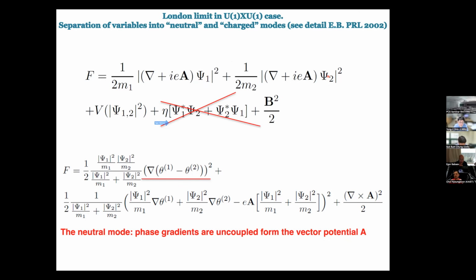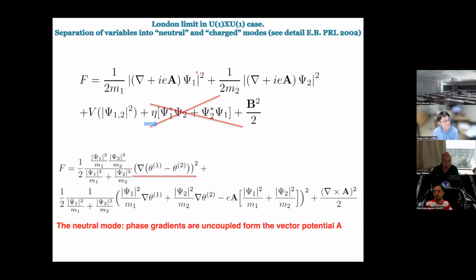Now, there is one important consequence of the fact that the two condensates are coupled by the same gauge field, and that relates to energy. There is one important energy aspect of topological excitations. The easiest way to see that, and if you want a detailed discussion there is a PRL from 2002 that discusses vortex energy in detail, is to take the London limit. Let us assume the psi's are constant, and then let us just rearrange the terms in this model, separating variables into the gradient of the phase difference of these complex fields and all the other terms.